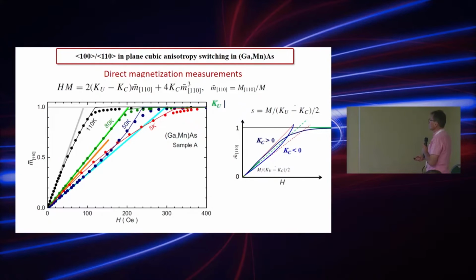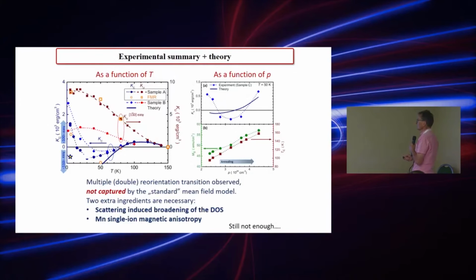Okay. So in the analysis of magnetization data, what is important, we just calculate the slope, this initial straight line. From this slope, we get the difference between these two parameters, and then we add only the curvature, so we can get the value of Kc, and we get Ku from the difference, which defines this initial slope. So actually, you don't need any parametric fitting of experimental curves. All you need is a ruler and a pocket calculator to calculate all the numbers.